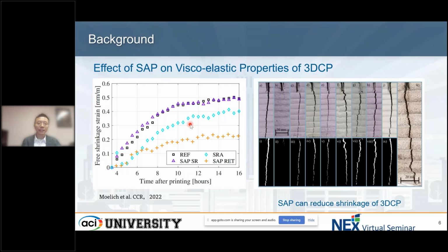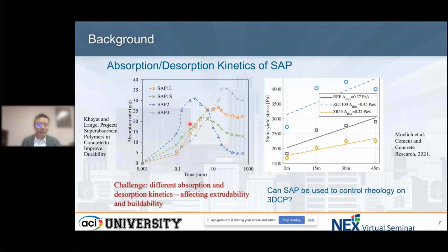But as it brings some advantage on reducing shrinkage, it also introduced some very big problems in 3D printing concrete. We all know that we need the printing concrete to be flowable when we pump it and when we extrude it. But after extruding the concrete, we need it to become hardened as soon as possible. But as I mentioned, SAP absorbs and desorbs water during the mixing, and it definitely will affect the workability and rheological properties of concrete. And so this became a big problem, and also a challenge.